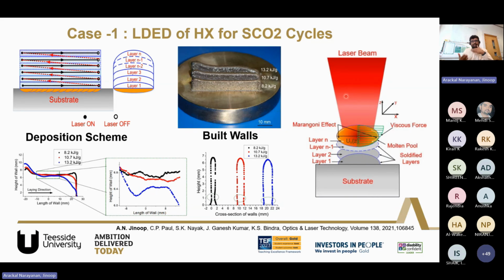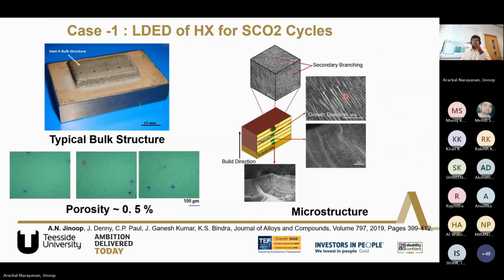We incorporated delay during the printing between the layers so that we can control the energy that is accumulated, which controls outward flow of the material. So this study was basically done to find that optimum range of parameters that we can use for the wall structures with optimum geometry and optimal material properties.